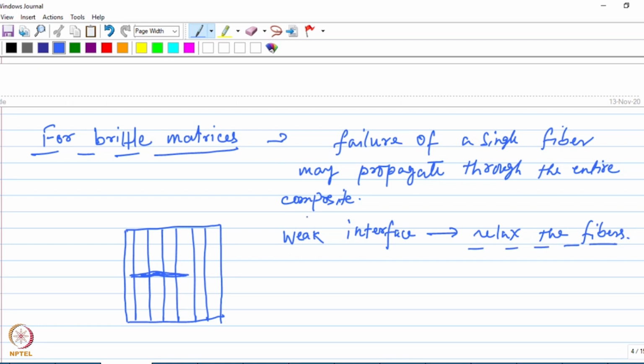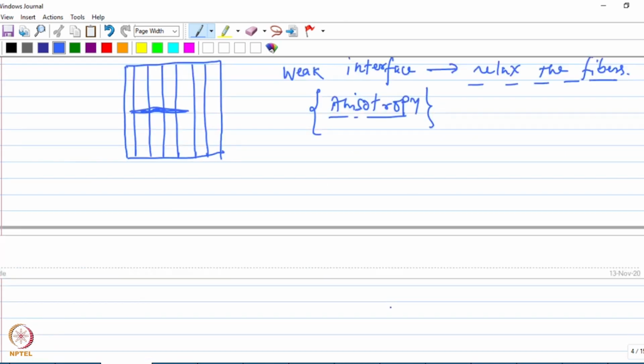And this is also one of the reasons for the anisotropy that you see in fiber reinforced composites. Because how this interface will behave from fiber to fiber might change, and it may also differ when you change the loading direction, right? So that is how this interface behavior can lead to anisotropy in fiber reinforced composites. So when the interface relaxes due to the weak bonding, it can be represented in this manner.